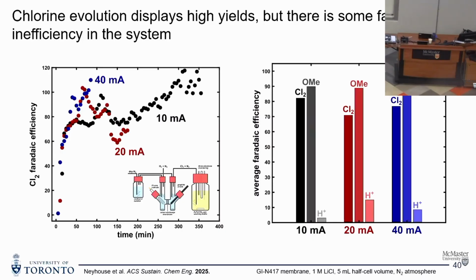And so this is actually another example where our membrane selectivity is hurting us. If we're more selective to something like lithium than acid, we would presumably have better yields. But we were pretty happy with these Faradaic efficiencies given we know what the side reactions are, and we would just have to put in a little bit of extra current, but we can still get the yields.